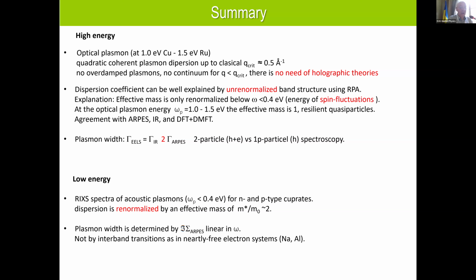And at lower energy, in RIXS, we see acoustic plasmons below 0.4 eV for n- and p-type doped cuprates, and also for the ruthenate. And at low energy, the plasmon dispersion is renormalized because there we have high effective mass. And the width of the plasmon in all cases is roughly a factor of 2 bigger than that of single particle excitations.